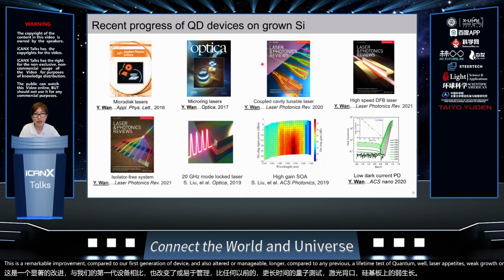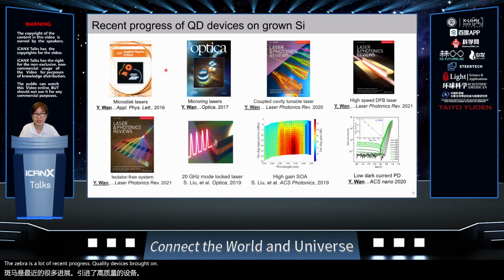There is a lot of recent progress on quantum dot devices grown on silicon, such as the sub-wavelength optically pumped microdisk lasers, sub-milliamp electrically injected microring lasers, coupled cavity tunable lasers, high-speed DFB lasers, and isolator-free silicon photonic transceiver demonstrations showing a path towards high-volume, low-cost transceivers that can be scaled to beyond 1 terabit per second. Also, 20 gigahertz mode-locked lasers with high channel count and excellent RF performance, high gain, high saturation output power amplifiers, and ultra low dark current photodetectors.